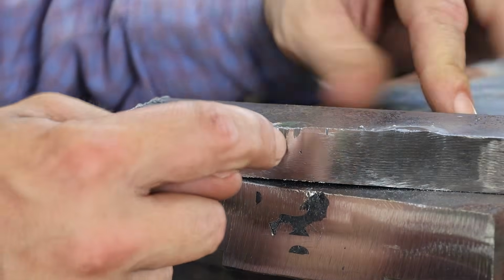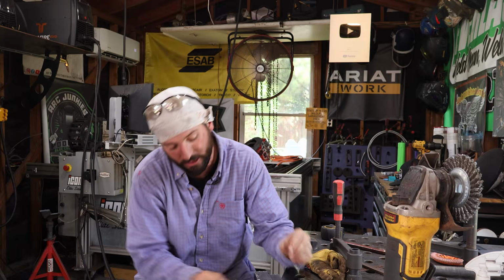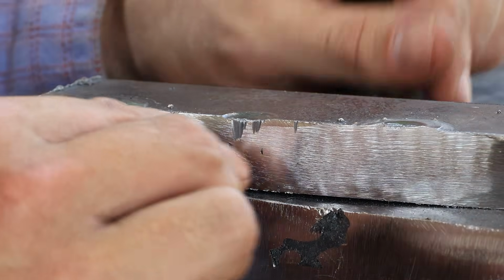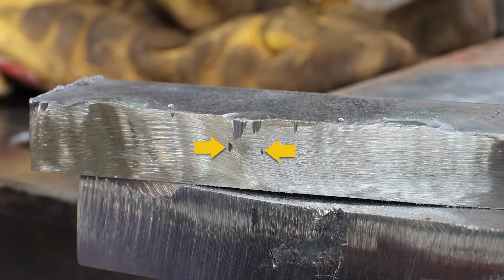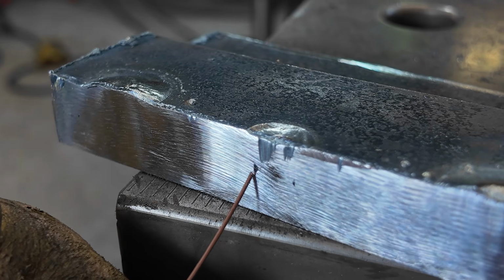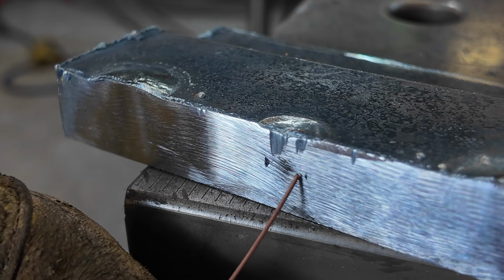Now when it comes to this little weld right here, that too small a hole, we didn't have enough space to get down there in time to get to those corners, so we can see clear as day trapped slag and lack of fusion in the corners of our plug weld. That's why it's important to have enough space and get that weld pool started, hit the root first, so that we can make sure we get fusion all the way around.